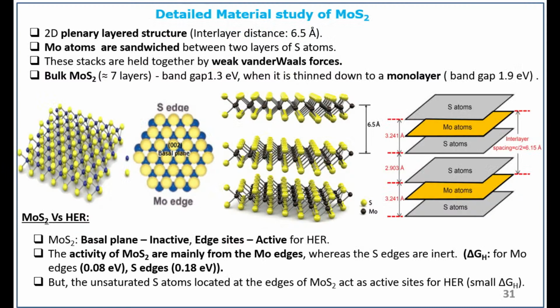we know that MoS2 is a semiconducting material, but as I said earlier, there is one more system, 1T MoS2. It's a metallic form, but the stability is not up to the mark, right? So we want to go in this direction also, because we know it's a 2D layer material. The distance between two layers is 6.5 Angstrom. If you go more than 7 layers of MoS2, it becomes like a bulk material. Its band gap is around 1.3.